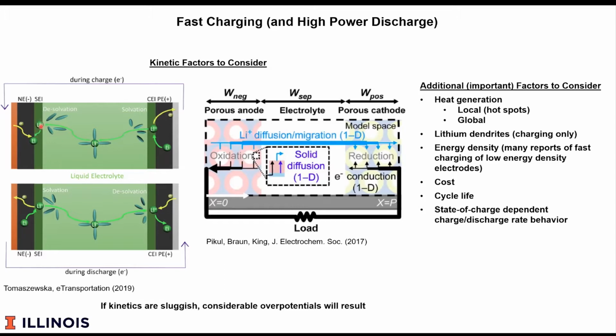Then the lithium has to diffuse into the electrode until it interacts with an electron and reduces. If the lithium is reduced too quickly, it may grow as lithium metal on the surface. If you have a metal anode, which is an area of research, that may not be a problem. However, if it grows too quickly, it probably still grows as a dendrite or grows as a needle. And if that needle comes across and hits the cathode, the battery tends to catch fire. So this lithium ion not only has to be able to desolvate, it has to then be able to diffuse into the anode host, which in most batteries today is a carbon-based host. And only then, after it's diffused into the host, does it become reduced to the lithium zero state.